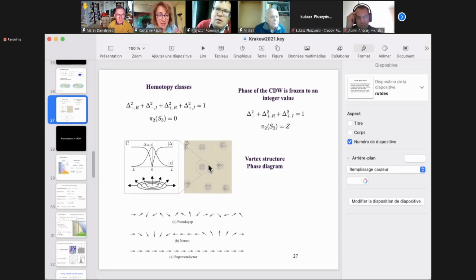Namely, the vortex is a topological defect. In terms of this pseudospin SU(2) symmetry, this is a skyrmion. So you see inside the vortex, I destroyed the superconducting order parameter. And since I have a skyrmion, my charge ordering parameter is going up. So here is the skyrmion representation.